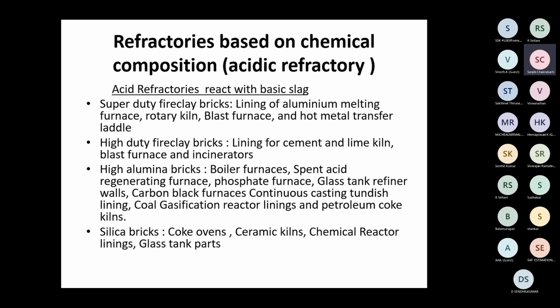So the basicity or acidity of the slag has to be determined before selecting the refractories. If you use the acid refractory, then you cannot use the basic slag. Or in a process where basic slag is generated, you cannot use the acid refractory. So you have to be very careful while selecting the refractory. So what are the acid refractories? I am defining them here.